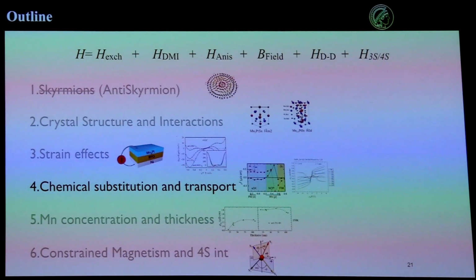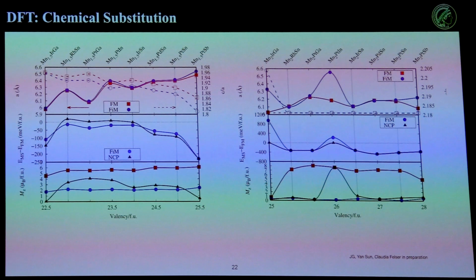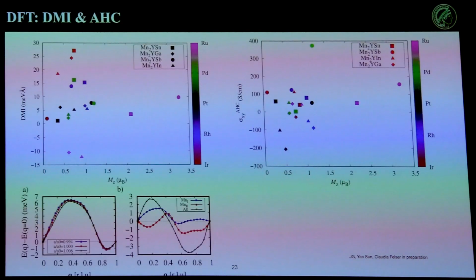Chemical substitution and transport. Here's pretty quickly. These are a lot of graphs, so don't worry about it. The main thing is that as you put in more manganese, you go from manganese 1.5 to manganese 2, you really do change how the structure behaves and what the fundamental interactions are. You also can change the magnetization, and you can also change the energetics of these systems, and you change the size of these systems a lot.